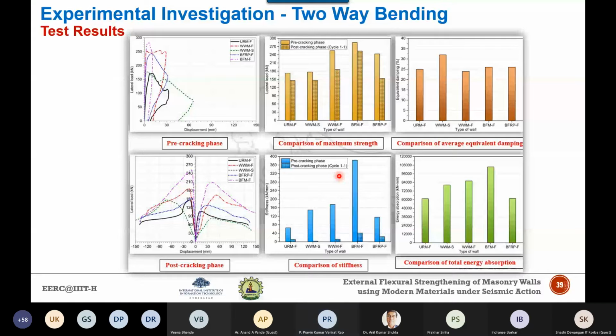So all the test walls have dissipated a significant amount of energy, as demonstrated by the hysteretic loops. Okay, so here you can see all the hysteretic loops, because of which the energy dissipation capacity was higher. And if you calculate the damping ratio for each wall, they are found in the range of 24 to 32%. So we have seen that all the test walls have shown that the techniques using wire mesh, fiber mesh, and fiber reinforced polymer can be used as a promising solution for retrofitting these masonry walls.